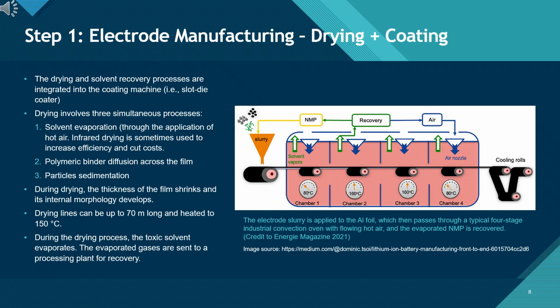Three things happen at the same time. 1. The solvent evaporates, carried away by hot air or sometimes infrared heating. 2. The polymer binder spreads evenly across the electrode film. 3. The active material particles settle into place. As drying continues, the coating layer shrinks and its internal structure develops. Ultimately, the solvent vapors, such as NMP, which can be toxic, are captured and sent to a recovery system, rather than being released into the air. The result is a clean, stable electrode layer, ready for pressing in the next step. The precision of this drying stage is critical. If it's uneven, the electrode can develop cracks, poor adhesion, or weak spots that affect battery safety and performance.